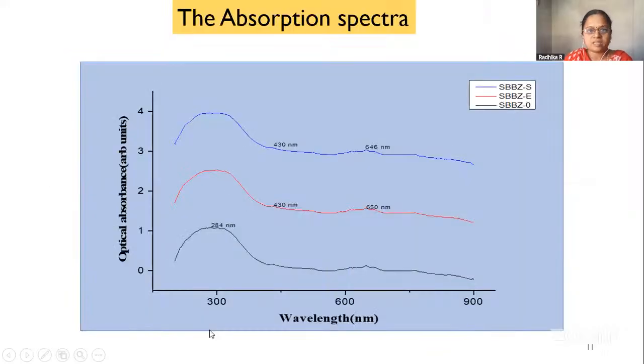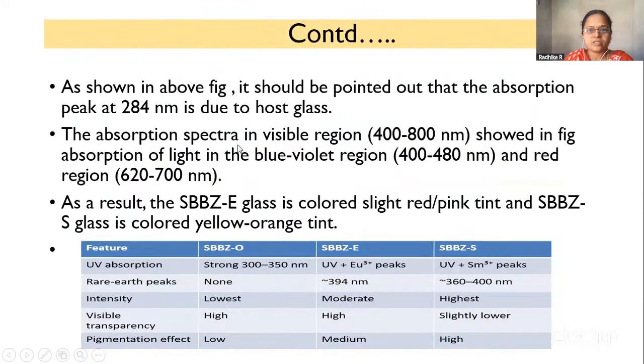And this is the absorption spectra. We analyzed that for my 3 samples. In that we can observe the broad absorption in the UV range, near 284 nanometer. It should be pointed out that the absorption peak at 284 nanometer is due to the host glass.